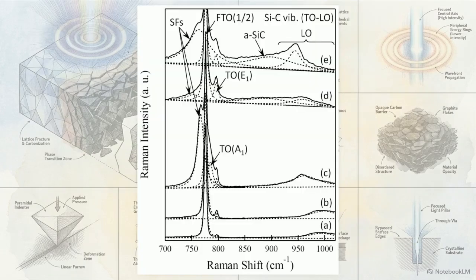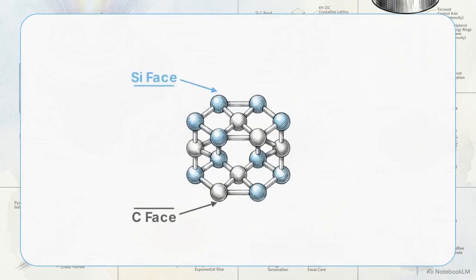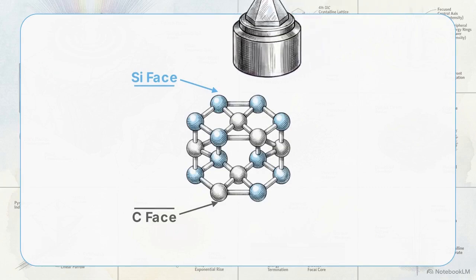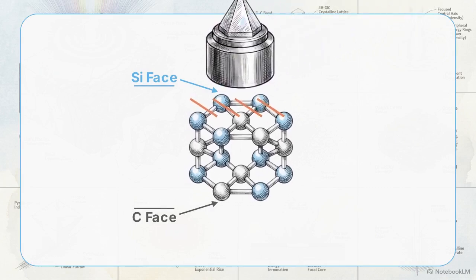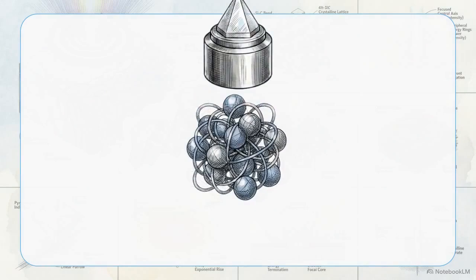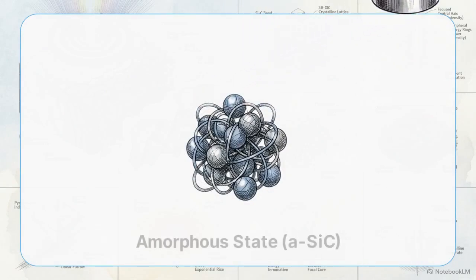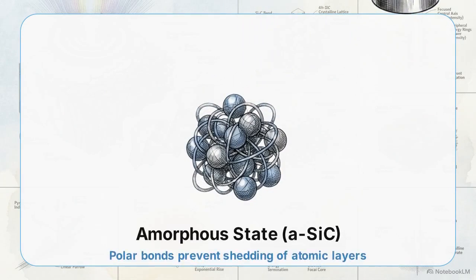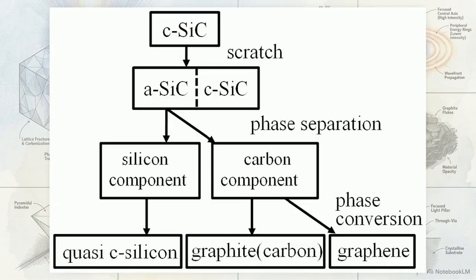Under heavy loads, a broad hump emerges between the TO and LO bands, spanning 800 to 950 inverse centimeters. This feature identifies amorphous SiC. Before the material ablates, the crystal lattice collapses into a disordered state. Because of surface polarity, polar SiC crystals cannot easily shed single atomic layers during this amorphization. This flowchart illustrates the resulting phase separation. The metastable amorphous SiC separates into distinct silicon and carbon components.